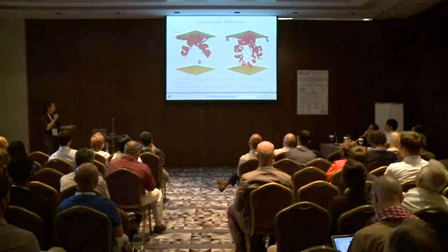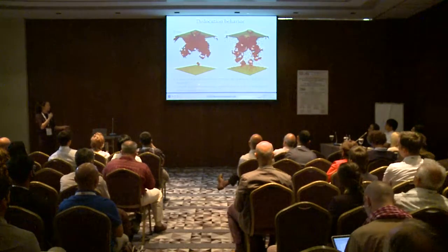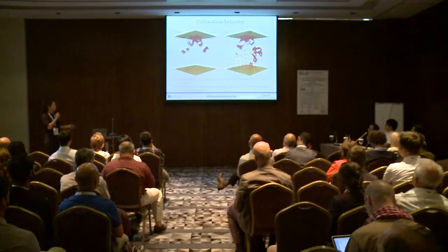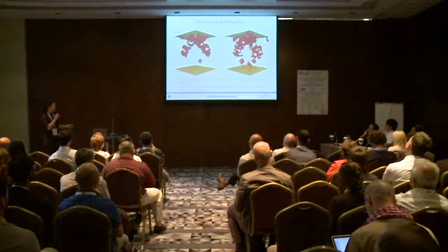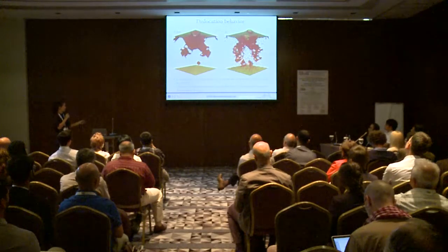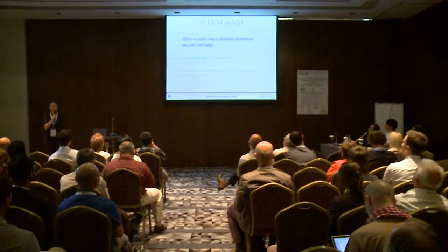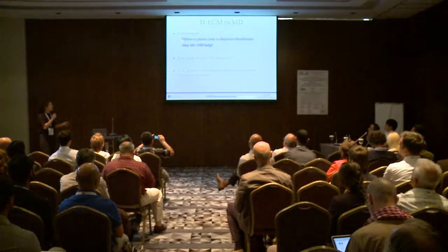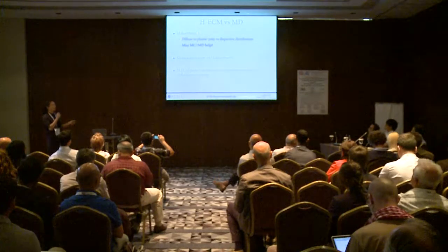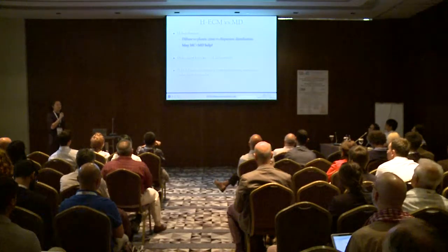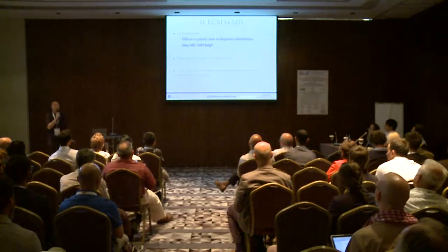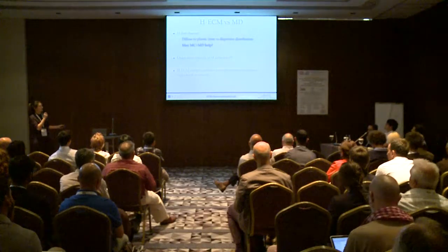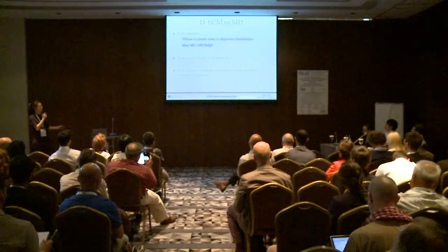So we can conclude that hydrogen atoms relieve the entanglement of the dislocation network and also reduce the pile-up of dislocations in the hydrogen-charged case. If we compare our continuum model with the molecular simulation, the continuum model assumes that hydrogen atoms tend to diffuse to the plastic zone and concentrate on the void surface, while in the molecular simulation the hydrogen atoms are more dispersively distributed.